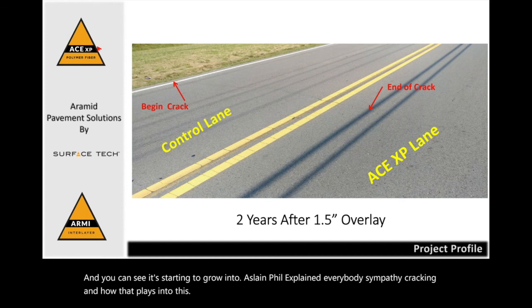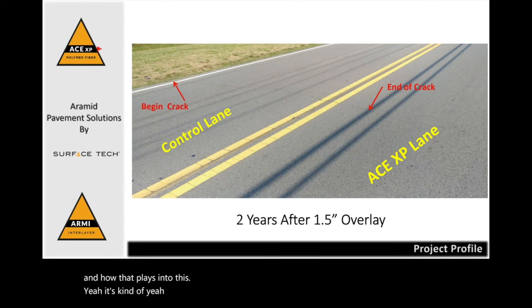Yeah, no problem, Joe. Sympathy cracking, I love the term. I used to see this when I would go do interlayer controls and trials. And what happens, the crack will move from one side over to the other, no different than putting an asphalt overlay down in a concrete curb and gutter area, wherever that crack is in the concrete curb and gutter. Have mercy, man, it will just always make that asphalt crack. So the only way to stop this is actually take a core at the end of that crack to stop it from going across.